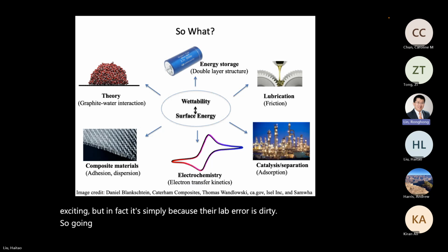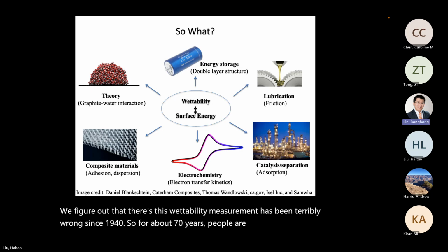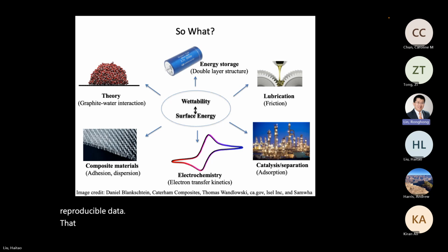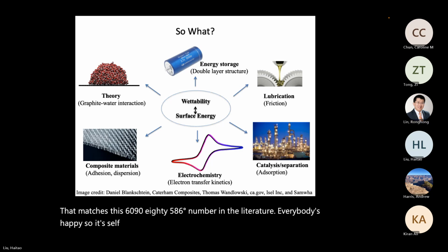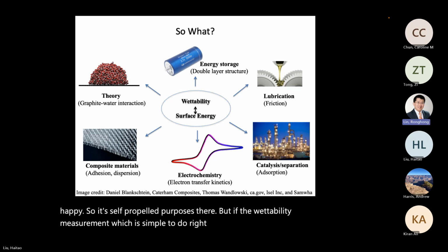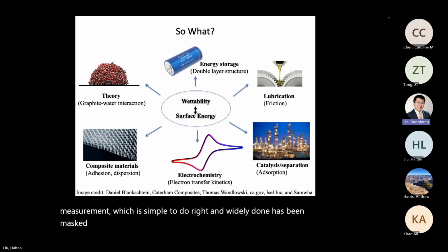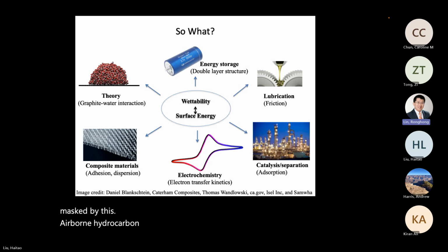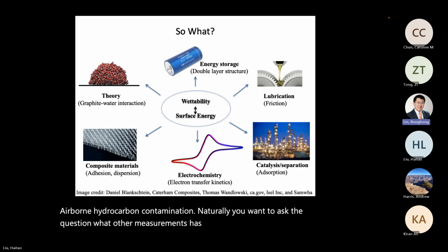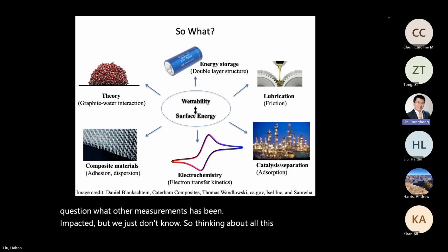So going back to the motivation page, at this stage, we figure out that this wettability measurement has been terribly wrong since 1940. So for about 70 years, people are publishing reproducible data that matches this 85, 86 degree number in the literature. Everybody's happy. But if the wettability measurement, which is simple to do, right, and widely done, has been masked by this airborne hydrocarbon contamination, naturally you want to ask the question, what other measurements have been impacted, but we just don't know.